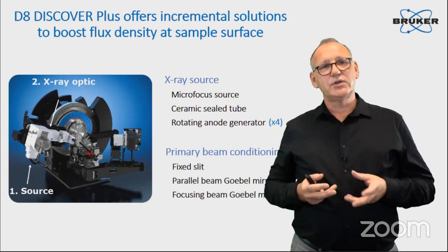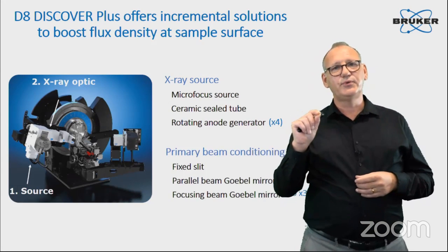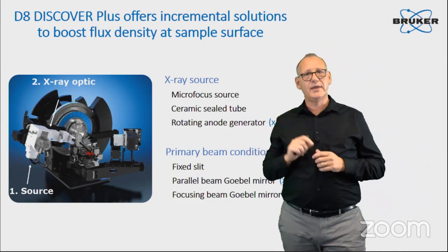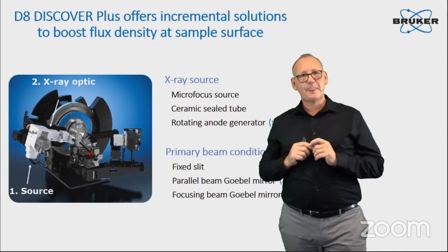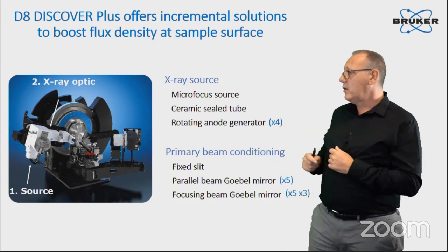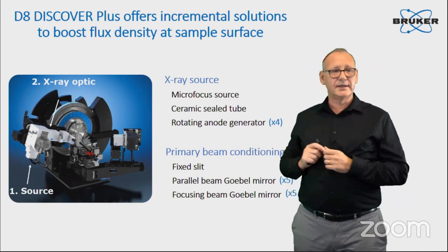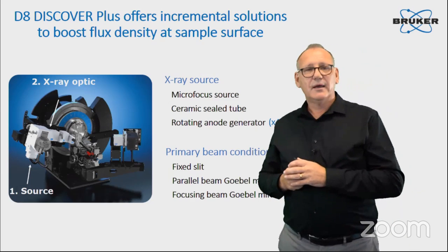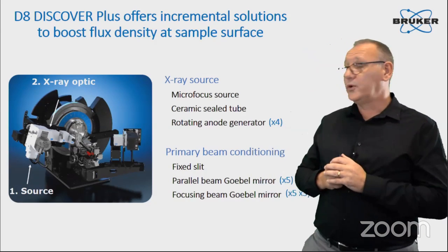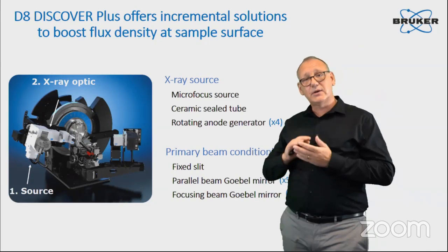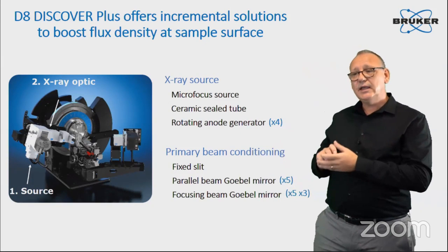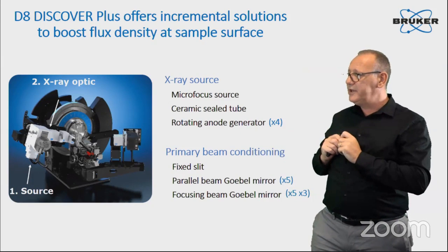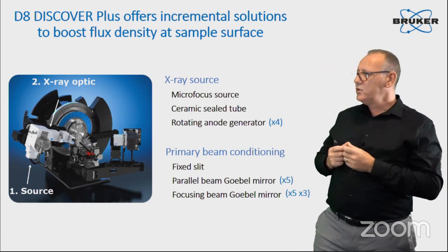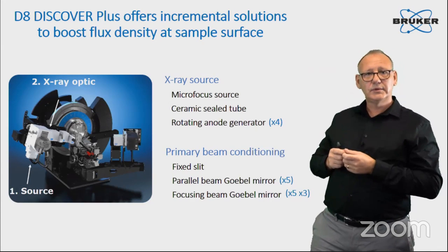Then you need to condition your beam. You remember, you have to put a very narrow exit slit at the exit of the beam in order to control your footprint. So the very first basic approach is just to have an exit slit that would probably be smaller than 0.1 millimeter to reach this beam size because the beam is divergent. If you want to condition the beam a little bit more, you can use X-ray mirrors. You can use a parallel beam Goebel mirror that will convert your divergent beam into a parallel beam.